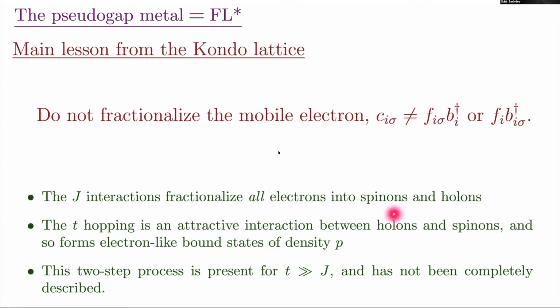And you do this to every electron. So that gives you some very exotic system, which has no electrons left. But then you say, well, the hopping is actually very attractive between holons and spinons. So maybe every holon binds a spinon, and you get an electron-like state, which is of density p. And these bound states form a little pocket. That, in a quick summary, is the summary of all those papers in one way or the other. And the argument is that this bound state formation must happen because t is much bigger than J. Okay, well, fine. I don't argue with any of these steps. In fact, I've written papers arguing for these steps. It's all right, but it's still extremely cumbersome.